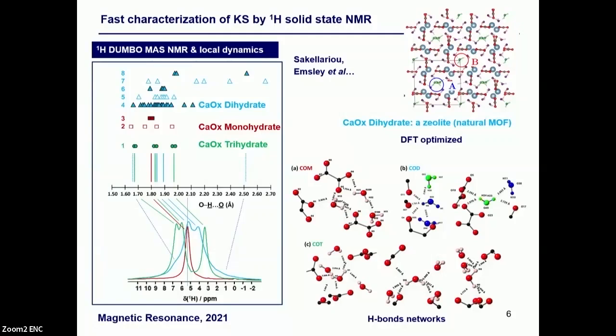And I show you here that if you use, for instance, DUMBO homonuclear decoupling, but you can use other decoupling schemes, it's really easy to distinguish the fingerprints corresponding to the monohydrate in red, to the dihydrate in blue, and the trihydrate in green. And in this case, it's even possible to assign the chemical shifts and to interpret the chemical shifts by taking into account, first of all, the structures of the materials, and we decided to optimize them at the DFT level in order to have the best description of the proton networks.